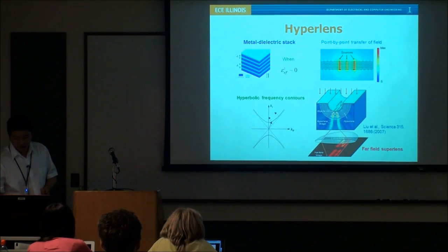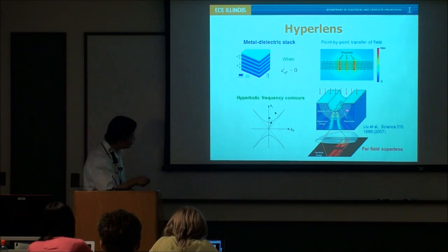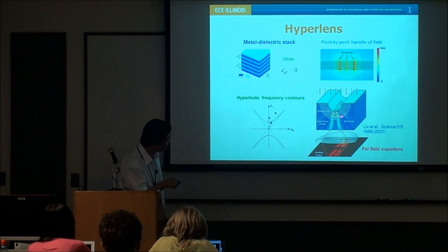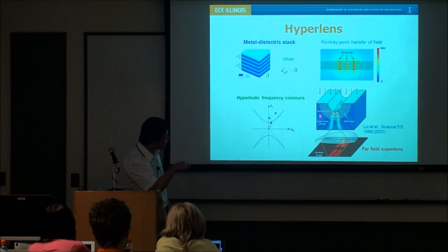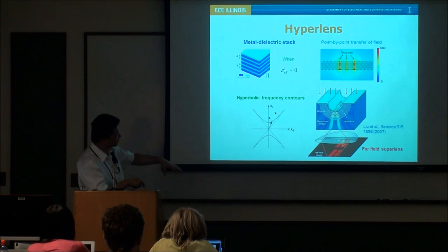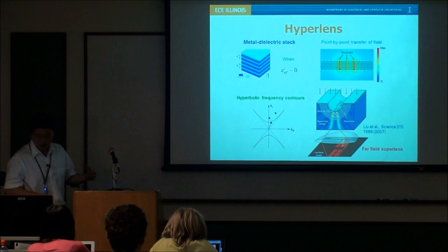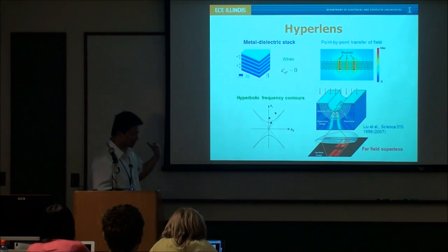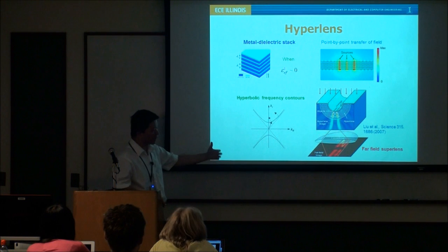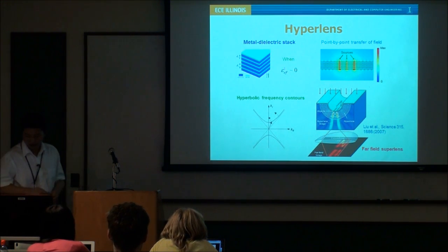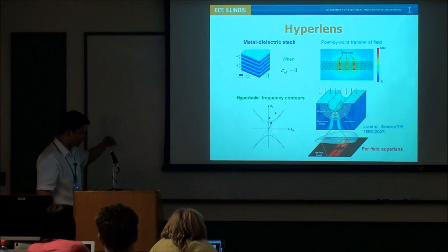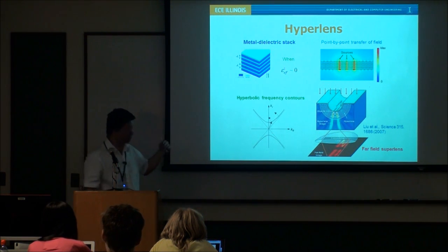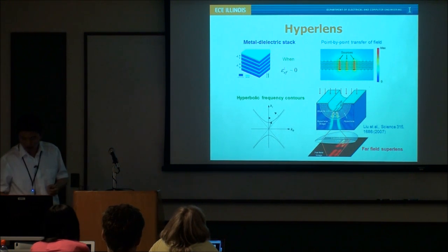You can also do this in the far field by creating multi-layer stacking structures. You have metal and dielectric alternating structures and bend them into a curve so that those nano patterns can be transferred to the far field. This is actually a very nice demonstration. You can use these structures to transfer the nanostructures into the far field without a lot of distortion and diffraction. This was not possible before, okay? And this really breaks the diffraction limit and brings the so-called spatial frequencies to a higher limit.